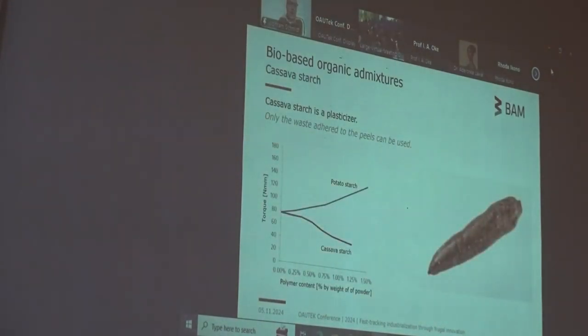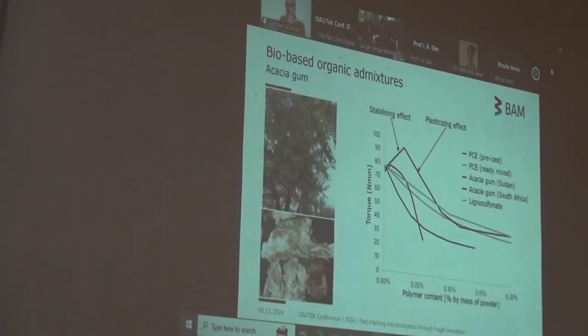Cassava starch, for example, has plasticizing properties. Here on the figure on the left side, you can see that as a comparison to potato starch, where when you add more and more starch and you mix your fresh concrete, you would see that the torque increases, so it's getting thicker. But if you use cassava starch, consistency becomes softer and we can reduce the water content.